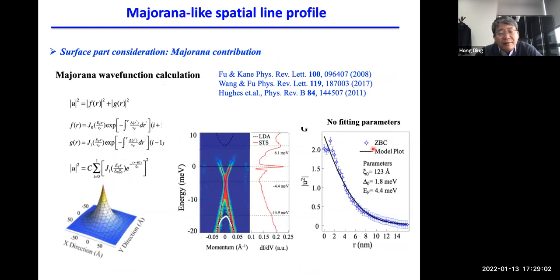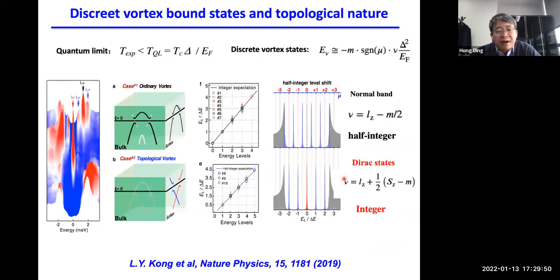And we can also describe our line profile by this simple Majorana profile. This was provided by Liang Fu, who is actually the first one to believe our story. And he immediately realized our case is very similar, or somewhat equivalent, to what had been proposed by Liang Fu and Charlie Kane. So this is the simple equation, and using the parameters obtained by experiments, both ARPES and STM, they can describe our spatial line profile very well.